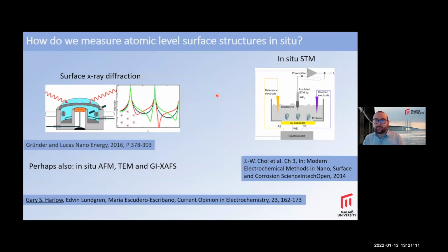But how do we measure surface structure in situ? At the atomic scale, there are only really two options. You have surface X-ray diffraction, or you have in situ STM. You can get some information, and quite successfully in some cases, from in situ AFM, TEM, and XAFS. But for single crystal surfaces, these are your two main options.